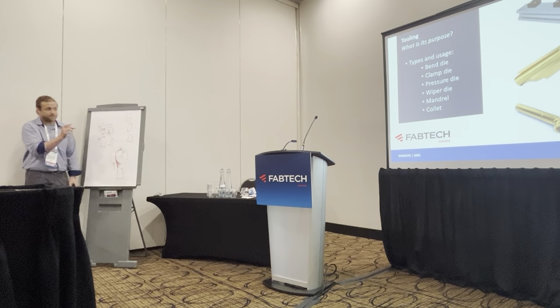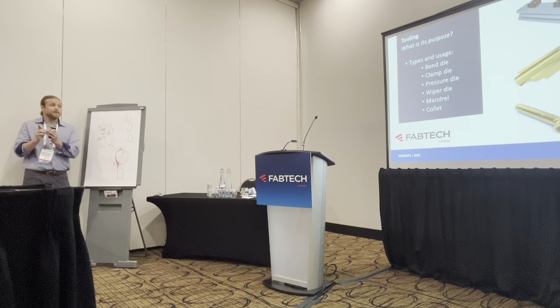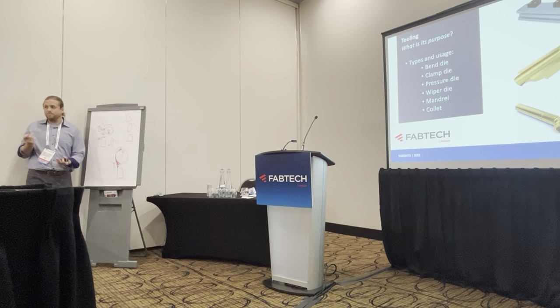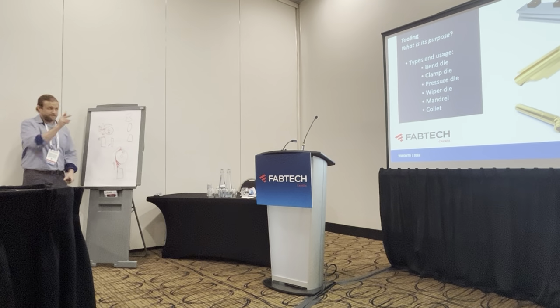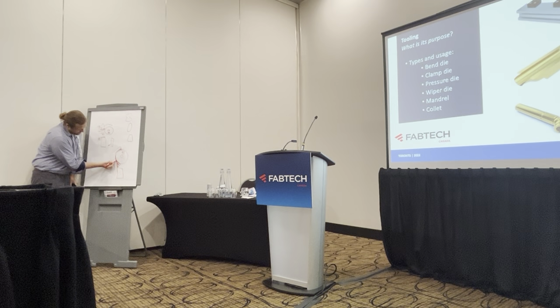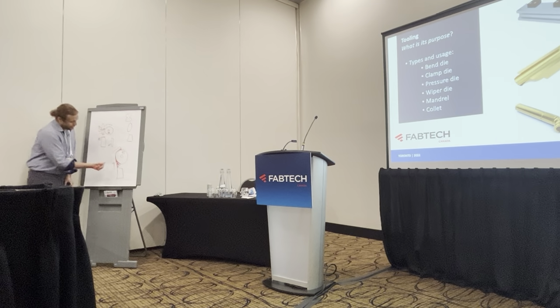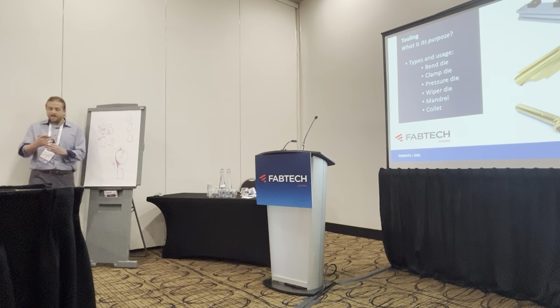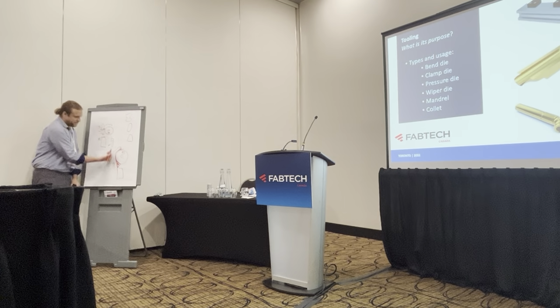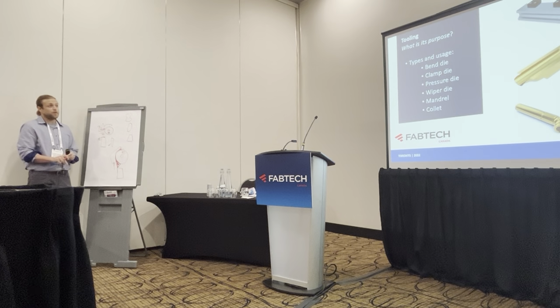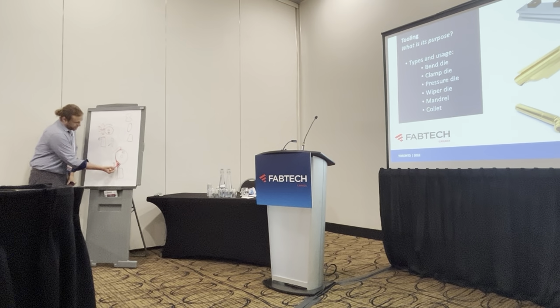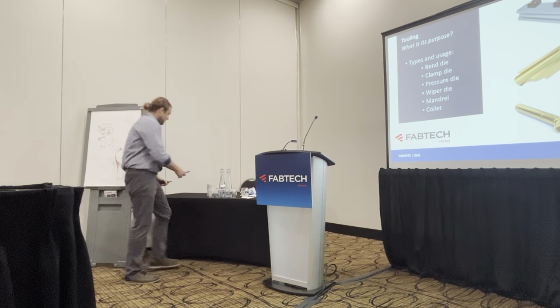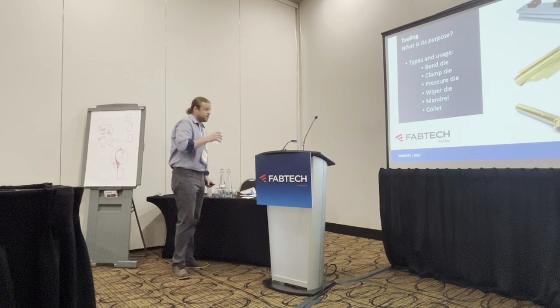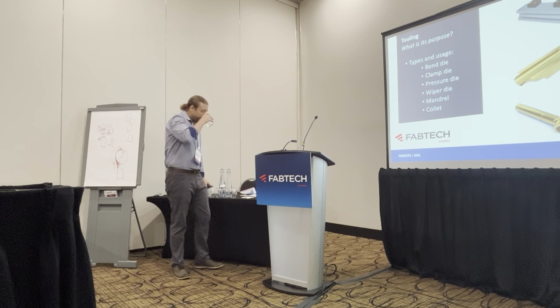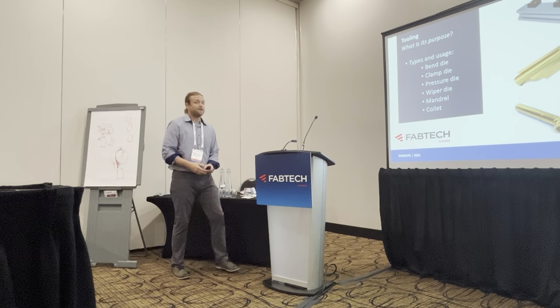So the idea of the wiper is, and that's why the tip is really feathered. It's a fine, real thin end. If you dropped it, it would break. It's that thin. And the idea of it is to feather that into the tangent point of the bend and close this gap up, telling the material you can't flow into this gap, you need to keep flowing in a linear direction. So that's where that wiper plays a huge role, is to eliminate that gap. And again, it's not an issue on your larger radiuses, but as you get down lower to that 1D bend, that's where you have to add a wiper.